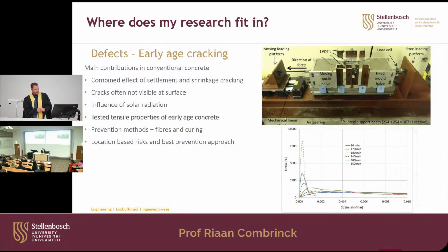Okay, then tensile properties. This is something I did for my PhD. We had to test the fresh properties of concrete, and this is quite difficult because concrete is flowable. So we developed this mold that floats on an air bearing, like an air vacuum here, and then it floats on top of that. You pull the two halves out of each other, and then you can measure the stress-strain relationship. You can get the tensile properties of it and its behavior, and then you can model it to see how much cracking can actually happen.